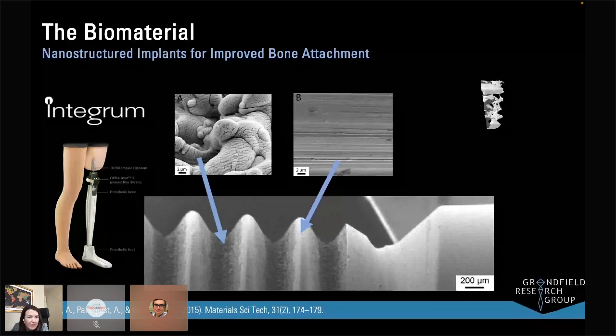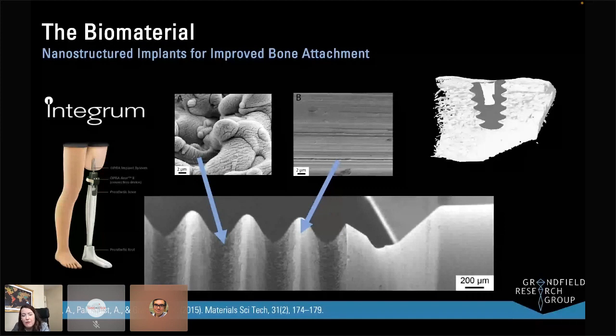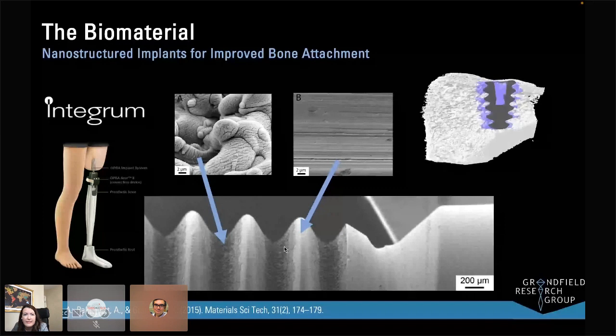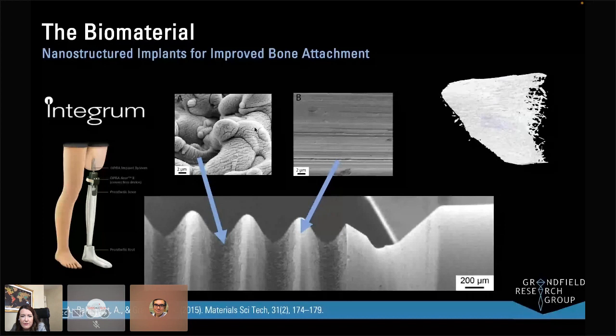It's used in dental applications, but also in bone-anchored prosthetic devices, as you'll see on the left here. The thread valleys of this implant have been modified to have a roughened nanostructure. This is a titanium dioxide-rich structure that forms on the surface after laser ablation.